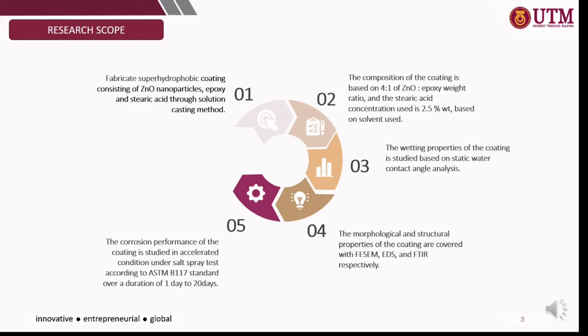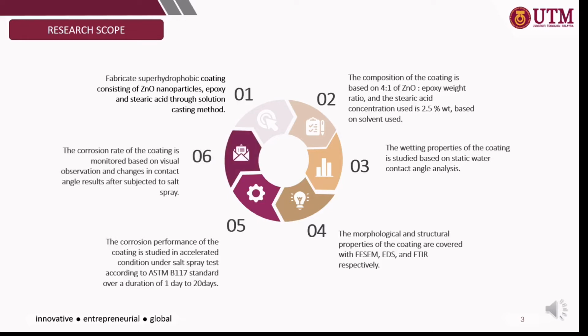The corrosion performance of the coating is studied in accelerated condition under salt spray testing according to the ASTM B117 standard over a duration of 1 to 20 days. And lastly, the corrosion rate of the coating is monitored based on visual observation and changes in contact angle results after being subjected to salt spray.